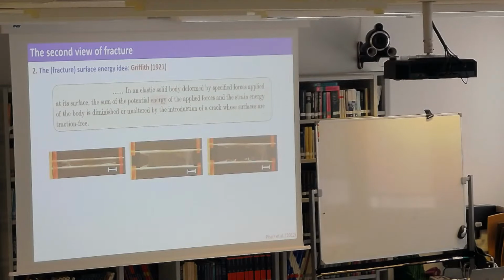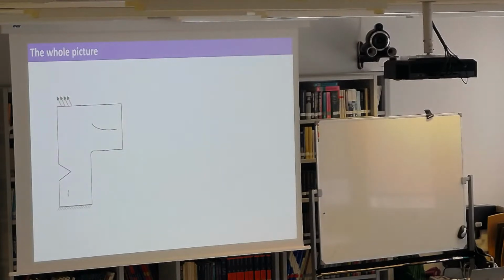And this is very different from strength, right? And if you actually do experiments, this is a piece of fancy elastomer with a pre-existing crack, and you apply the force, this works, right? And so there is experimental evidence that this works for this case. But it doesn't work in general, because if you don't have a pre-existing crack, this idea is simply not what happens in reality. So we have strength as one limit, we have Griffith as the other limit. Of course now, we are 100 years after, right? 2021. We do have a whole picture experimentally of what happens. So the whole picture is as follows.